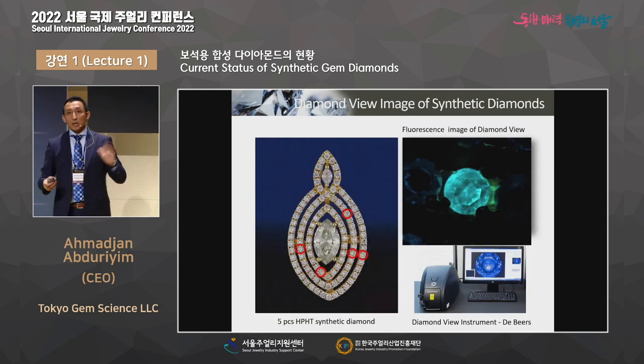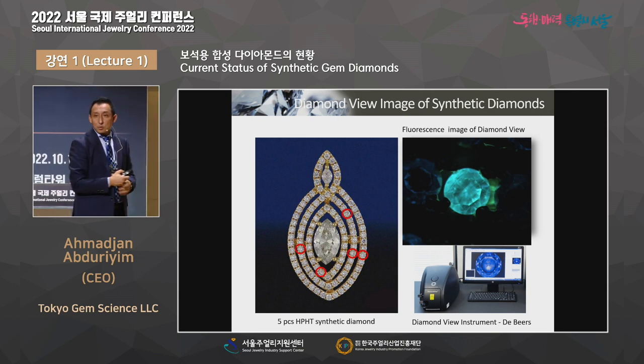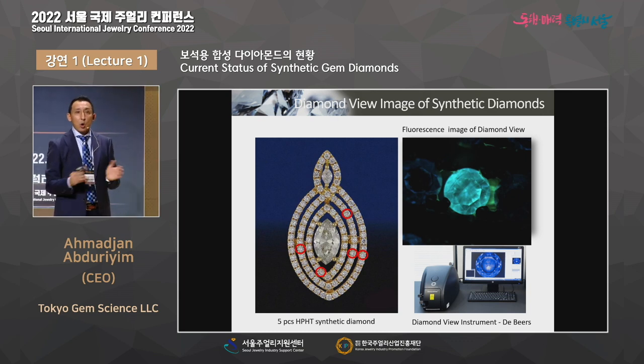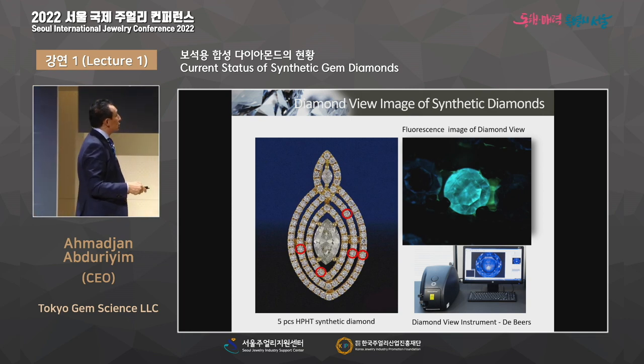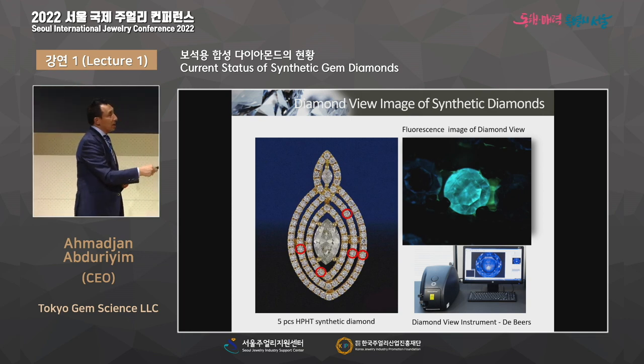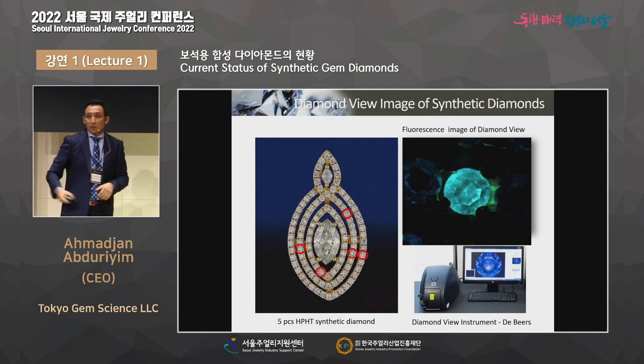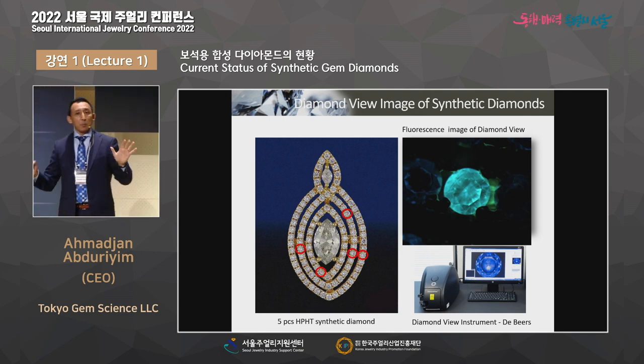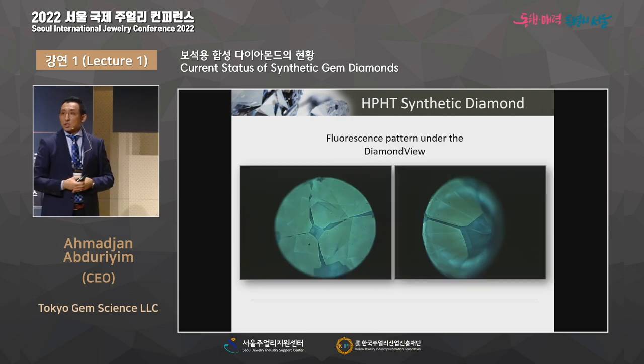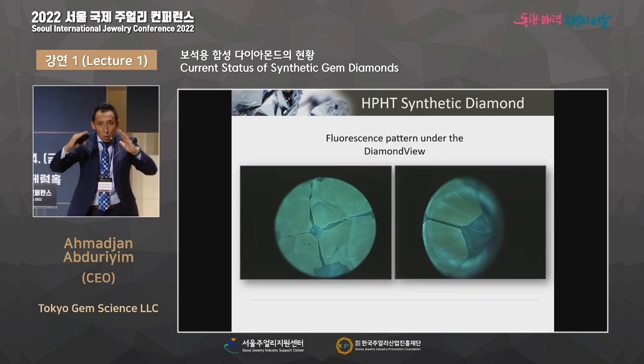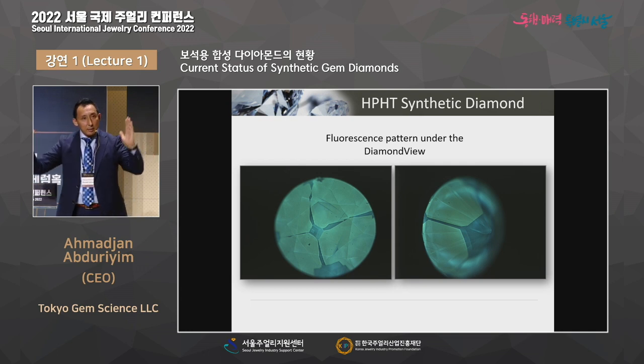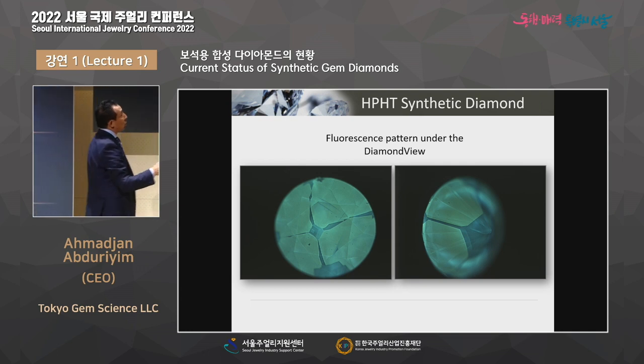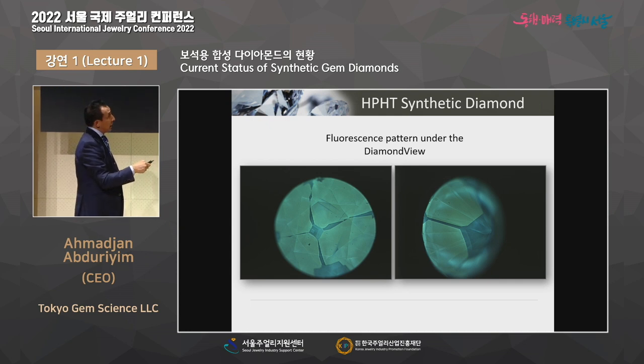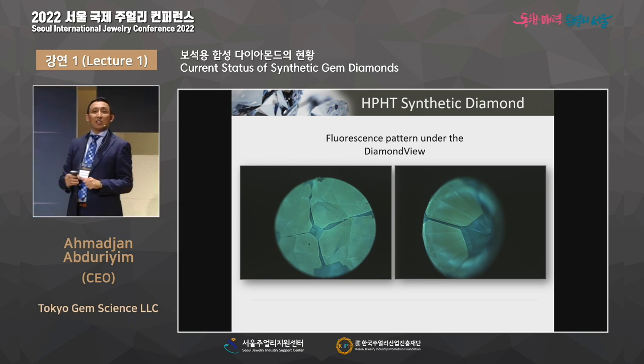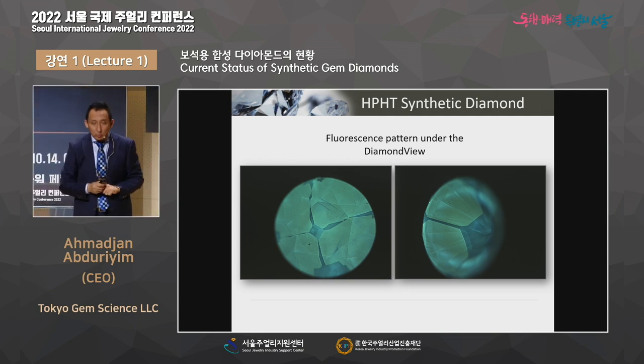Again, in this jewelry, the five pieces are synthetic. Can you tell that? No. So normally it's lab people, gemologists, who will test that. And we have the DiamondView instrument. Also, we can look at the growth structure. Natural diamond is totally different from synthetic diamond. Synthetic diamond grows in metal, as I said, metal flux. They have a very stable structure, like octahedron and cubic directions. So this kind of growth sector can definitely show you the difference from the natural.